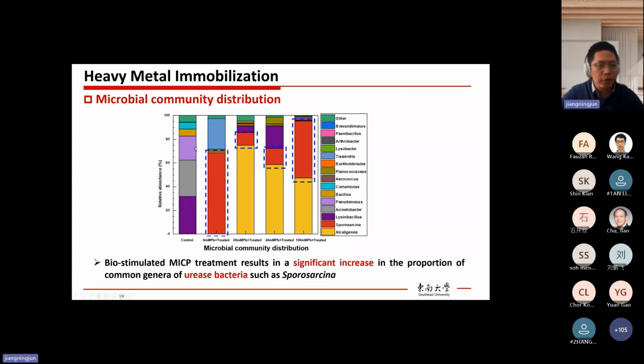Okay, then we also analyzed the microbial community distribution. So for the control case, we don't see dominant species. Then for the case with MICP treatment but no contaminants, we can see Sporosarcina dominates. Then for the low contaminant concentration case, we can see the amount of Sporosarcina becomes smaller, but we see this one, right? This one has become dominant.